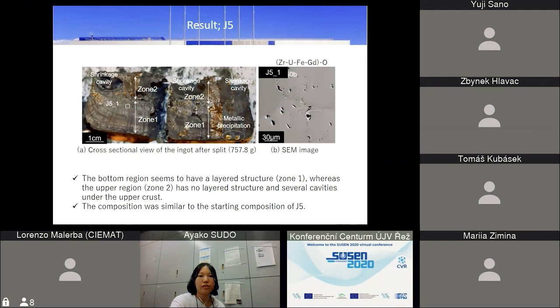Next is the result. This is the cross-sectional view of the ingot, solidified ingot after split. And this cross-sectional view shows two zones, zone 1 and zone 2. The bottom region, zone 1, seems layered stripe structure, and the zone 2 has no layered structure, and it has several shrinkage cavities and upper crust. This is a SEM image of this J51 region, and it shows zirconium, uranium, iron, gadolinium oxide polycrystalline structure, and the composition was similar to the starting composition of J5.